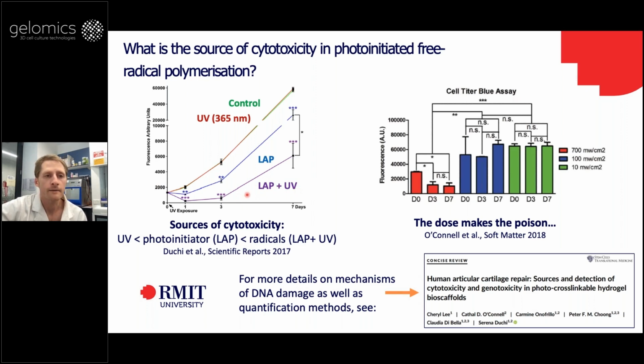And in our particular experiments with our particular cell type, we didn't see any noticeable loss in cell viability, as measured by metabolic activity, when we shone the UV alone compared to control. But coming back to this free radical generation, it's not just the presence of free radicals. Obviously, the dose makes the poison.